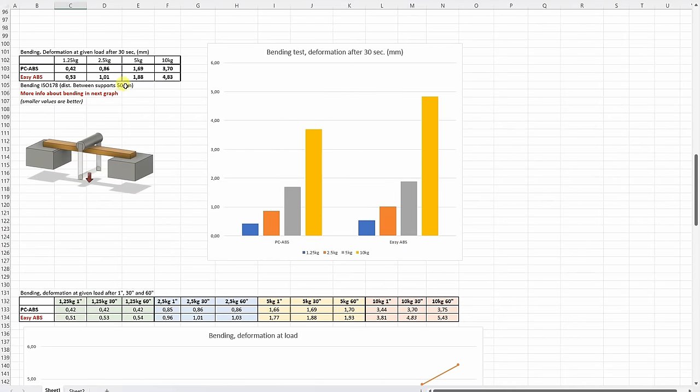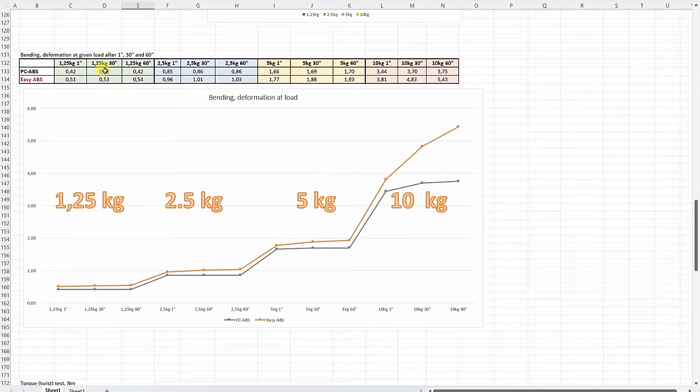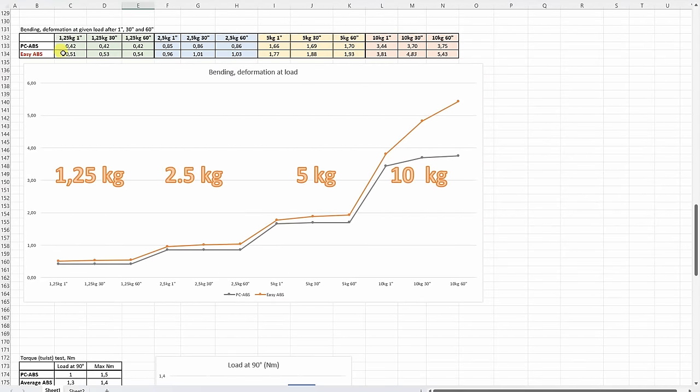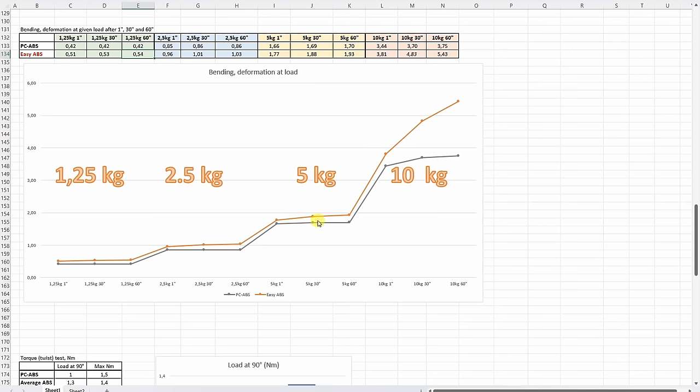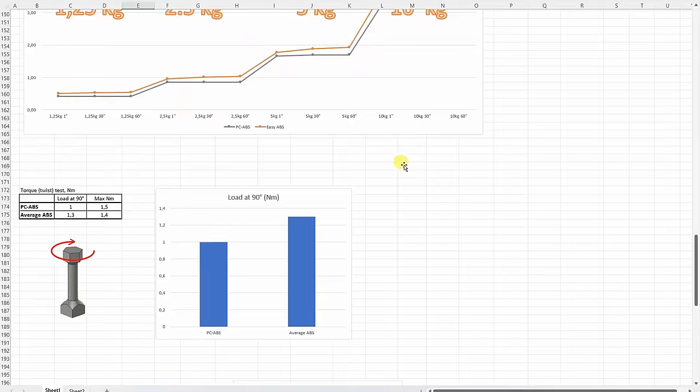And now three point bending test. And here you can see the deformations under a given load after 30 seconds. But maybe this is more important and interesting information. Now important to mention that I don't have ABS measured with this new bending test. So only I have this easy ABS which acts more like PETG. But well this is what I can compare. So these are the deformations under these loads after 30 and 60 seconds. And what we can see when it is almost horizontal that it doesn't deform under this load. And when we have some small angle this means it creeps, it continuously deforms under this load. And we can see for this PC-ABS it is somewhere between 5 and 10 kilograms where it doesn't creep under that load.